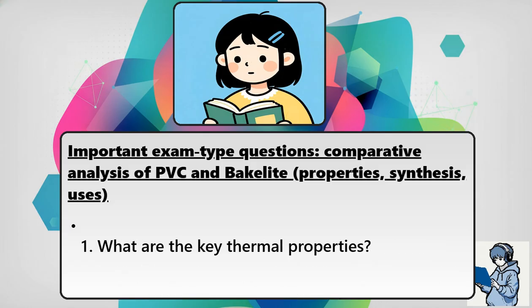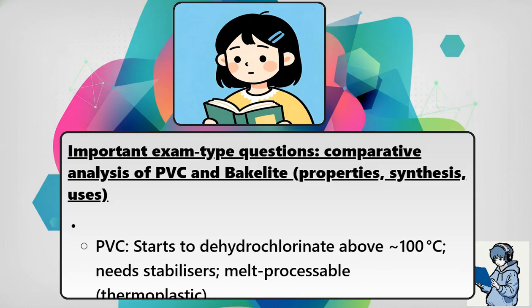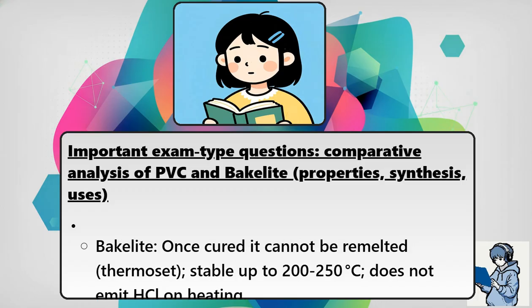3. What are the key thermal properties? PVC: starts to dehydrochlorinate above 100 degrees Celsius. Needs stabilizers. Melt processable thermoplastic. Bakelite: once cured, it cannot be remelted. Thermoset. Stable up to 200 to 250 degrees Celsius. Does not emit HCl on heating.